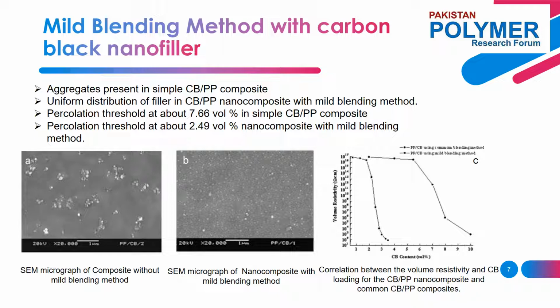A conductive network formed in the common composite at high loading of carbon black due to the close contact of aggregates. The percolation threshold at lower loading of carbon black in the nanocomposite prepared by the mild blending method could be explained by the tunneling conductivity mechanism. In the carbon black and PP nanocomposite, the carbon particles were dispersed as primary particles, located apart from each other and enclosed by the PP, which is an excellent insulator. This arrangement satisfies the requirement of tunneling conduction.